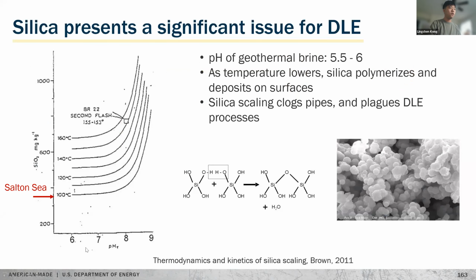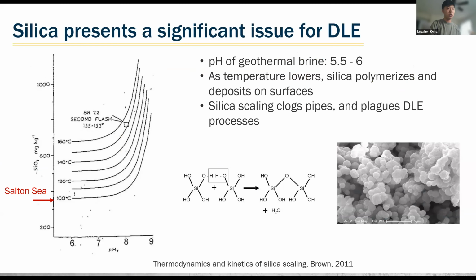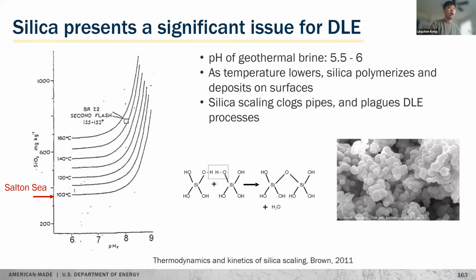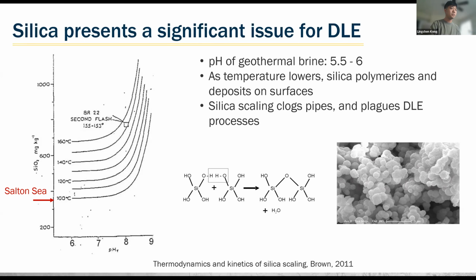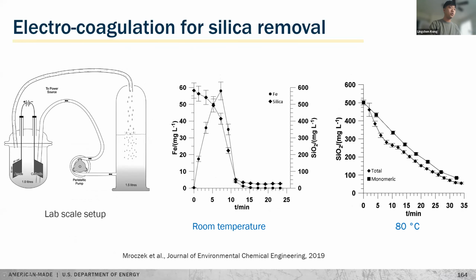Next slide, please. Firstly, we know that the Salton Sea geothermal brine has around 340 milligrams per liter of silica, and the geothermal brine pH is around 5.5 to 6, and the temperature is around 100 Celsius. We all know that after flashing, the silica concentration will increase, and after the geothermal brine is cooled, the silica solubility decreases very much and leads to the formation of silica scale. And because other ions are also present, such as iron and aluminum, such metal silicates will form as precipitate. And it will become an issue for the following lithium extraction. So we propose to remove the silica first. Next slide, please. Yeah, so electrocoagulation for silica removal, this is what we propose to use in the first step.